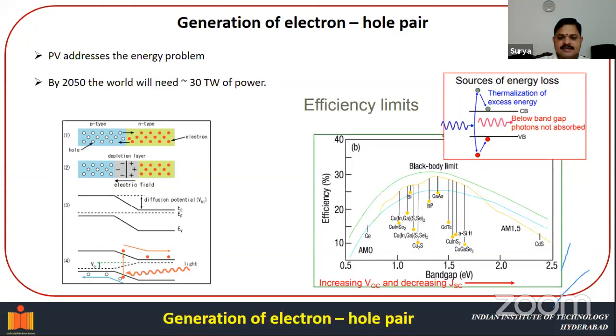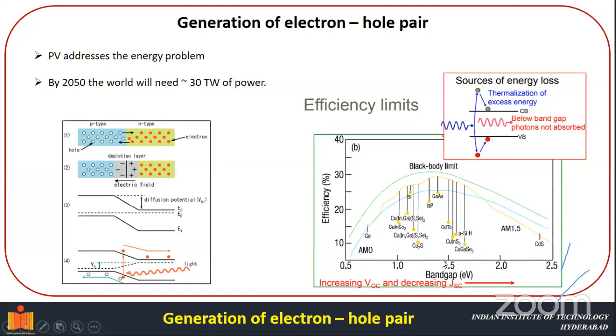The reason is that, as I mentioned, whatever light that we receive from the sun will not come at one energy. You will have a broad spectrum. So different materials will respond at different energies. Like for instance, depending upon the band gap of the material, some materials would respond at one energy, some materials would respond at another energy. So that's why we have to use different materials to convert the sunlight to the electricity. Like for instance, silicon has a band gap around 1.1 or so, whereas gallium arsenide has around 1.4. CuGaSe2 has a band gap around 1.6. So the absorption capacity of different materials will be different. As a result, different semiconducting materials can be used for solar cell applications.